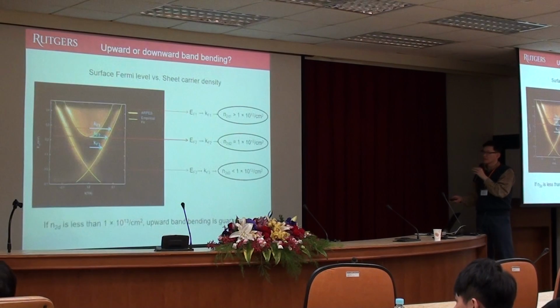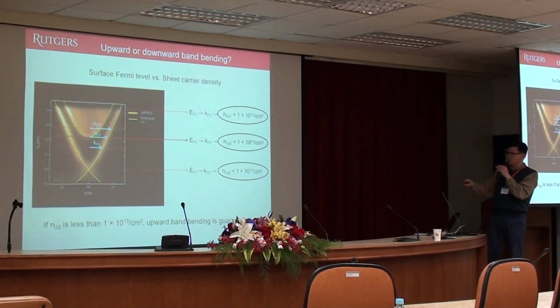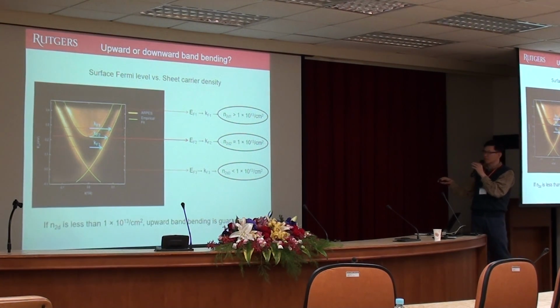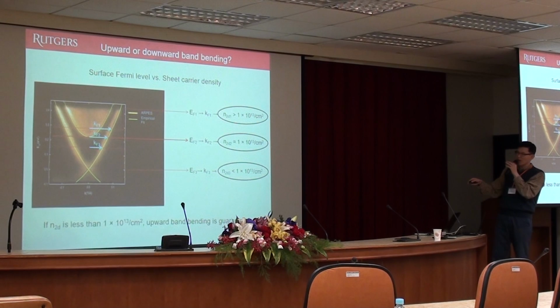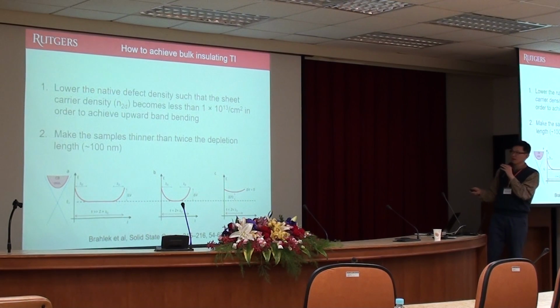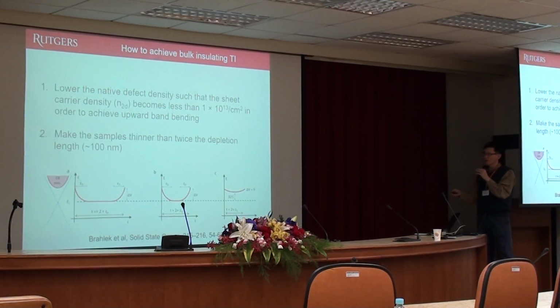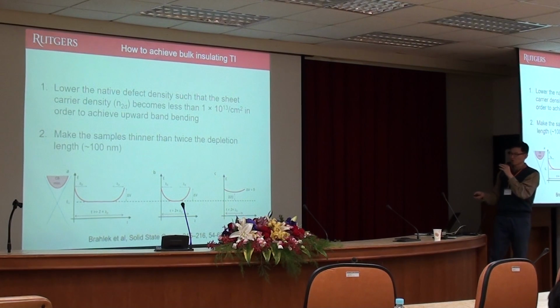So again, if you look at the same thing from ARPES, this is 10 to the 13 carrier density. If carrier density is higher than 10 to the 13, then your bulk is metallic. You have the Fermi level that crosses your band, your bulk, so you have downward band bending. That's not good. But if your carrier density is lower than 10 to the 13, then you have upward band bending, and you can now, by making the samples thin, in principle achieve the bulk insulating sample. So roughly, this is basically repeating the same thing.